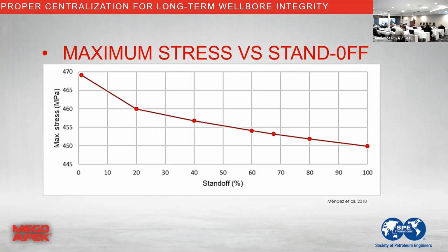You're going to get the highest maximum stress in your cement system, whether that is done empirically or whether that's done through finite element analysis. That's what you're going to see. There's a red dot. All dots are red, by the way, but there's the one red dot between 60 and 80, closer to 70 rather. That's the recommended standoff that API preaches, 67% standoff. If you're within that region, yeah, your maximum stress is not brutally altered and the impact is really minimum.